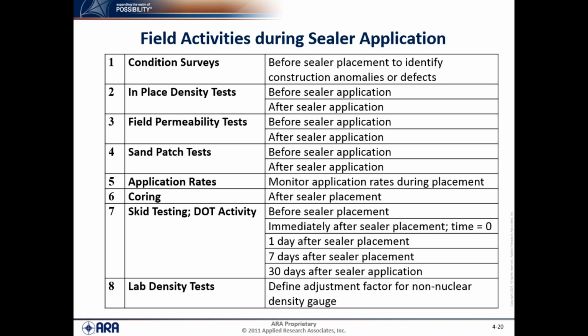So cores were done. The reason we did cores was to basically measure the bulk specific gravity of that core to calibrate the PQI non-nuclear density gauge. So those were basically used for calibration purposes of the non-nuclear density gauge.